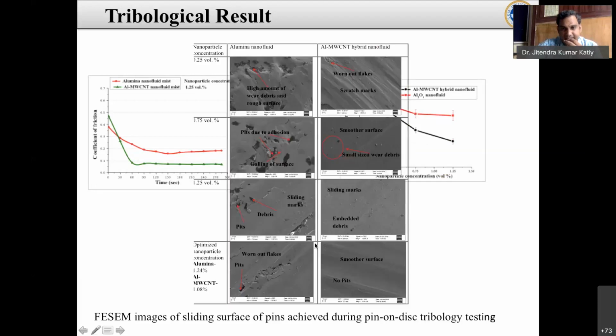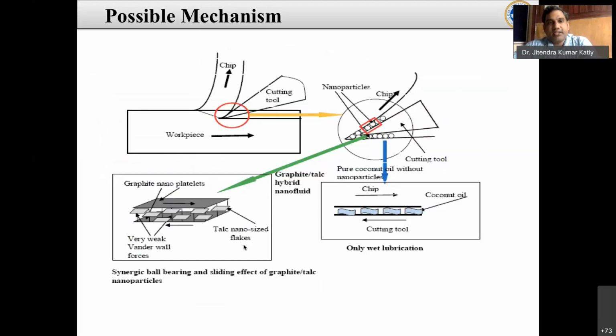So these are the surfaces obtained. These are the optimum results. You can see no pit formation, a very smooth surface compared to the other concentrations of the particle. This is the optimized one, the 1.25% concentration, and this is the 1.75 volume concentration. These are the observations after the pin-on-disk test. This tribological analysis with the pin-on-disk is only for understanding the behavior of the cutting fluid that we use in machining through minimum quantity lubrication. The possible mechanism is the same here as well, and this paper is also published in Friction, which has an impact factor of 5.2.